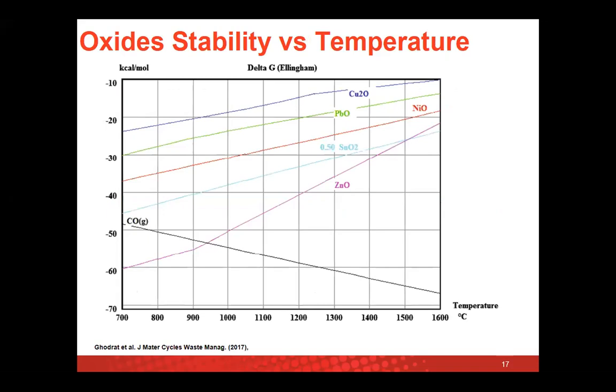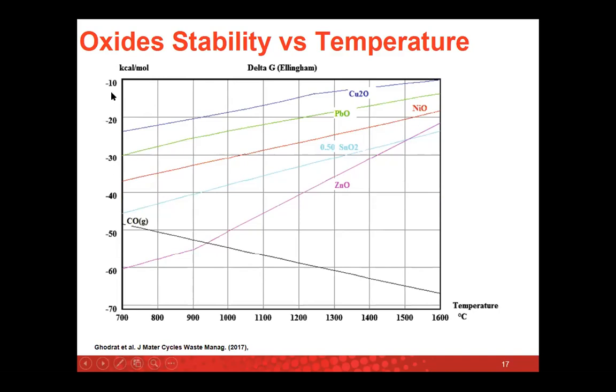As metallurgists, pyrometallurgical engineers, this diagram for how we do the reduction process is very well known to us. This is called the delta G Ellingham diagram, which gives the stability of oxides with temperature. We can see that minus 10, minus 20, this is the delta G value for the oxides. We know that a more negative delta G value means that compound or substance is more thermodynamically stable at that particular condition.